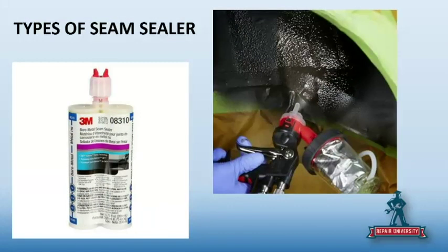And you've got to keep one more thing in mind too: any one of these sprayables or any type of pumpable, whether it's pneumatic or electric or just a regular hand manual type pump, you've got to practice at least some portion of a bead, especially with the sprayable seam sealers through some sort of atomization, where you have to practice what kind of bead you're going to have. Do I have to move a certain way, half circle, little round circles, jitter back and forth to get that same duplication? Sometimes I've got to put out masking tape. This is all stuff that you have to add to the damage report when you're writing it up, because look, I have to do this stuff. So there's corrosion protection, but there's also the cosmetic side of seam sealer. Well, you've got to realize corrosion protection is usually something that dries.